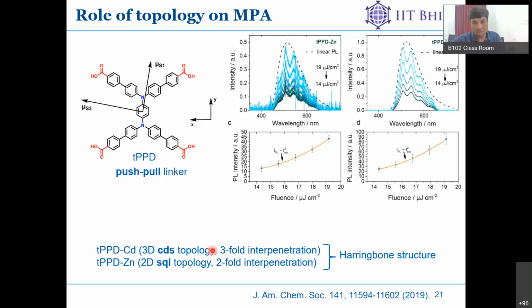Then we tried to measure the values and started observing the absorption cross sections. The question is, does this compound show any two-photon absorption cross section or not? We plotted it using fluorescence intensity, and we see the intensity of fluorescence is quadratically related to the intensity of excitation of the laser. So this shows that this is a two-photon excitation.